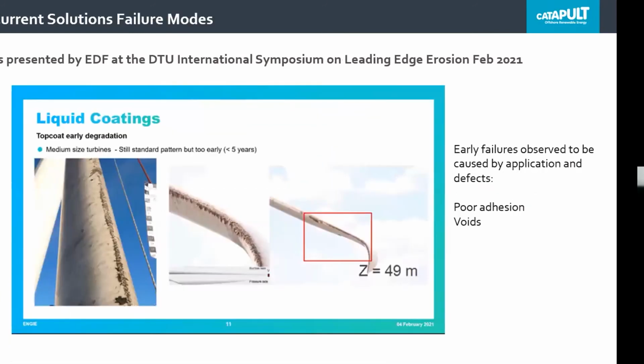EDF also turned around and presented some of the failures. So here, a quick look at liquid coatings: what they're seeing is that they're getting the same erosion patterns that they got on the old products, even with the new products, but it's happening in less than 5 years. I guess the current information, which is quite sketchy, is that some of the new products that I showed you on the first slide are lasting less than 1 year. And they're generally observing early failures caused by the application process or by defects. A lot of them are failing by poor adhesion or by voids.